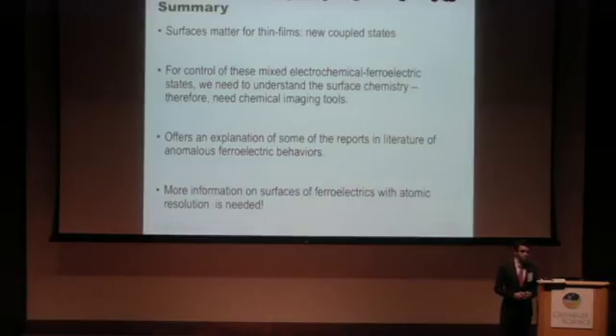Would like to ask about the film strontium titanate on dysprosium scandate. So you claim that the polarization hysteresis loop is just artificial in this case, but you measure polarization out of plane of the film. Yes. But in this case, the strain is tensile and the polarization should be in the plane. So can you comment on it? It should be polarization in the plane there. There is also dielectric anomaly in the plane and not out of plane.